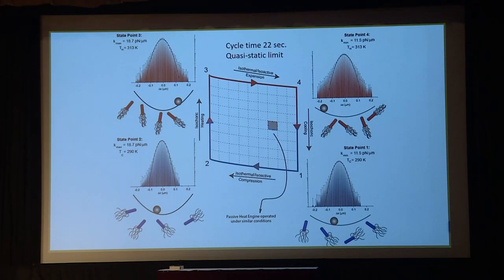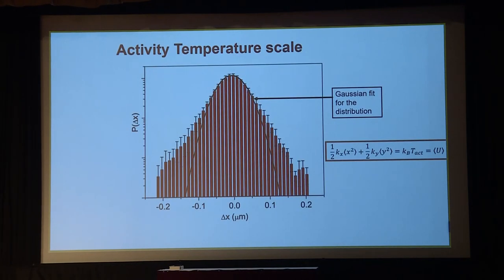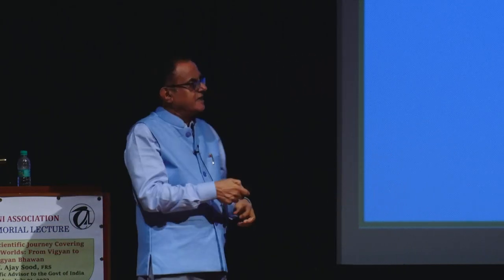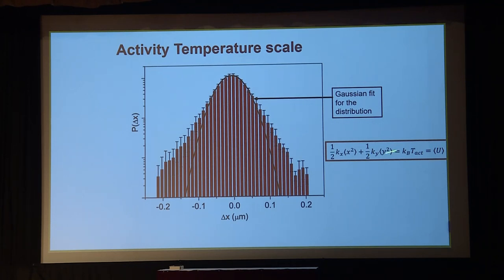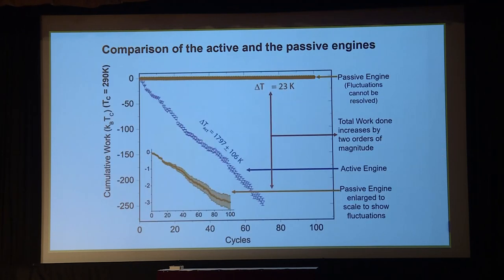But using this bacterial activity to get a high effective temperature, how do we define it? Because you have to define some bacterial activity. The probability distribution is well fit by a Gaussian. Using this variance, the width of this, we can simply equate to kBT. This T is not the temperature of the reservoir. It is the effective temperature seen by the colloidal particle, because bacteria are putting in all this noise, and that noise is getting converted into this heat. And this is what we did at that time.